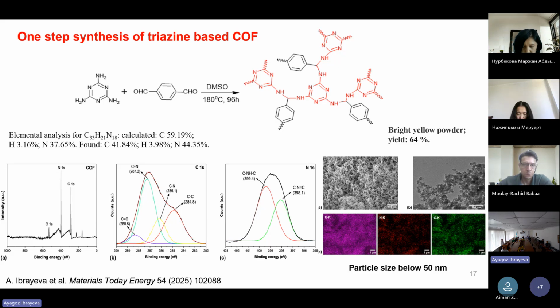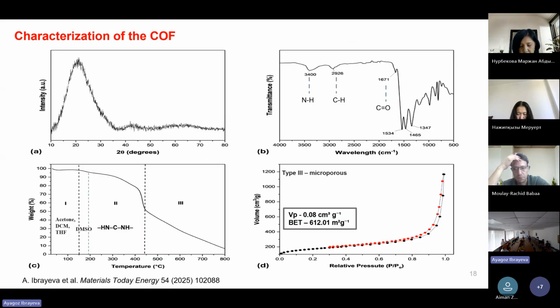Here we can see that it has spherical morphology and particle size below 50 nanometers. Further, on the XRD, we see one broad peak, which gives us information that it has an amorphous nature. And by FTIR analysis, the main functional groups in this framework were evaluated. It is NH, CH, and CO functional groups.